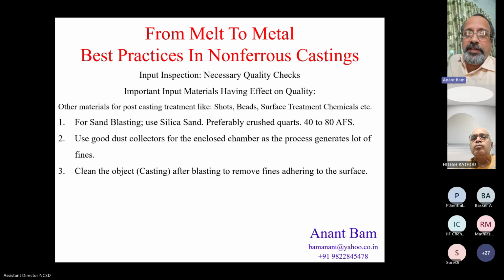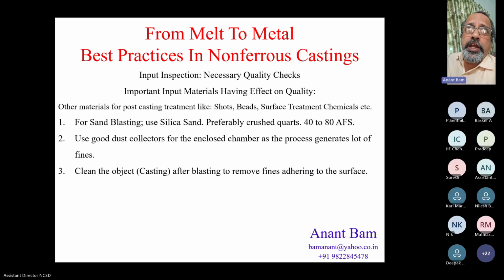The recommended sand is silica sand. Any silica sand can do, but preferred is crushed quartz due to its slightly higher hardness, and due to being artificially manufactured, it is more angular, more sharp, and hence it creates a smoother surface in a shorter time.